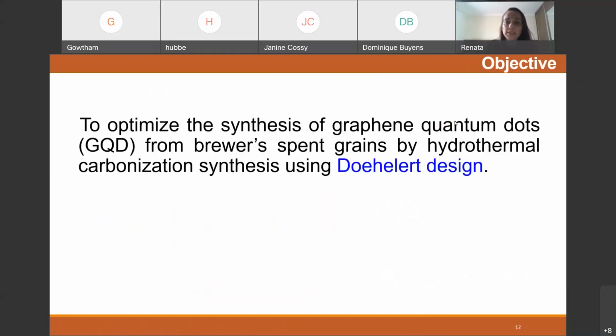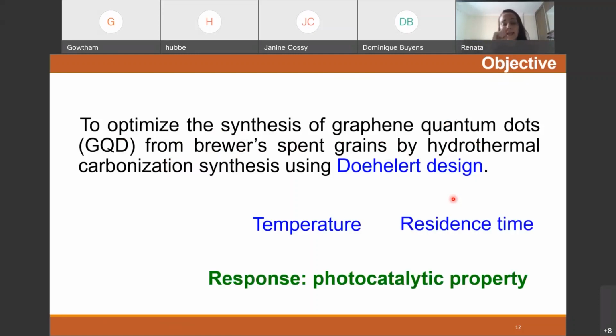So the object of this work was to optimize the synthesis of graphene quantum dots from brewer's spent grains by hydrothermal carbonization synthesis using a Doehlert design. For this, we evaluate two variables, the temperature of the process and the residence time. To evaluate the best characteristics of the materials, we evaluate the photocatalytic properties.